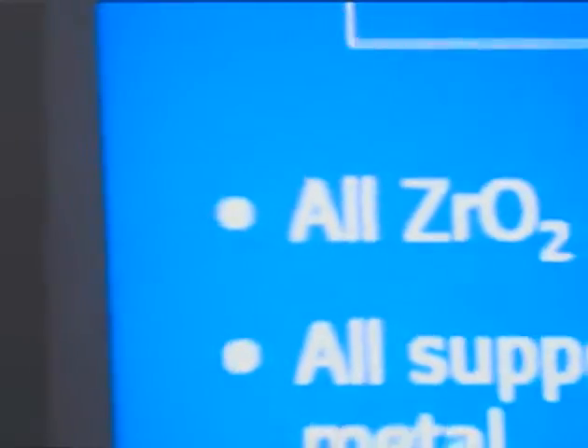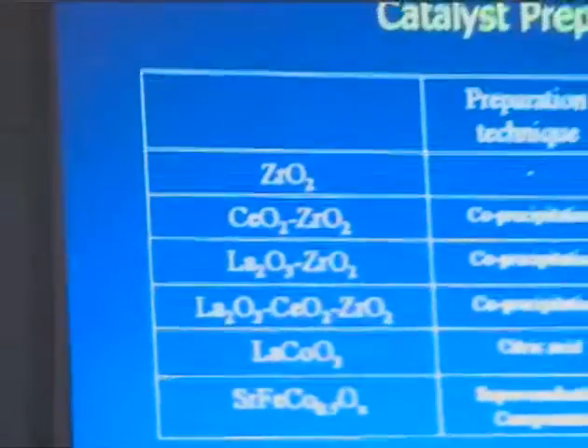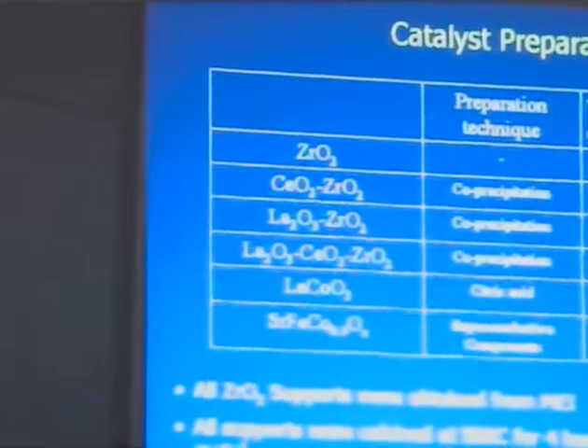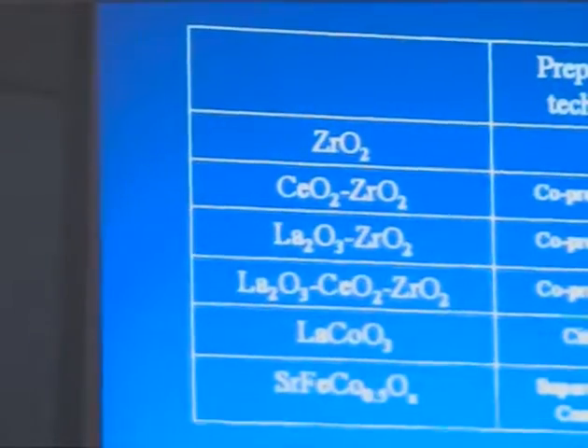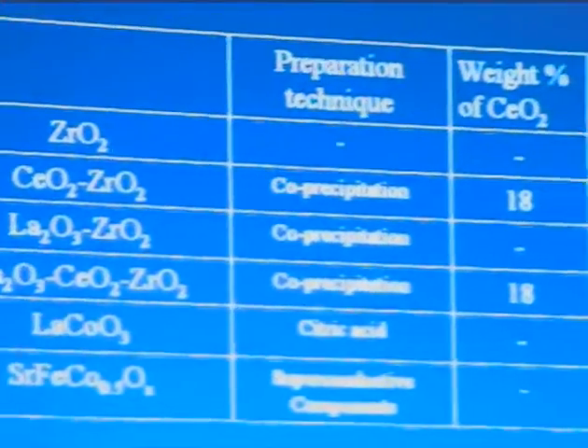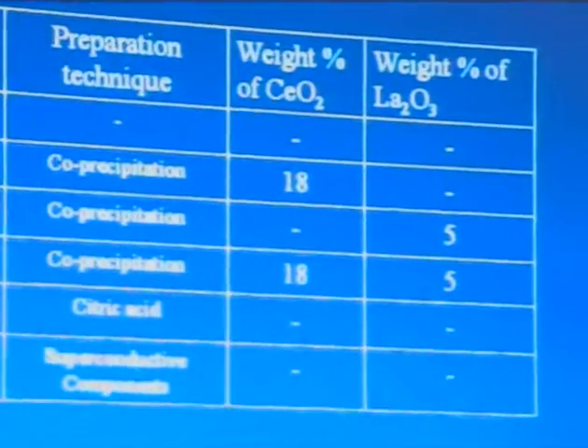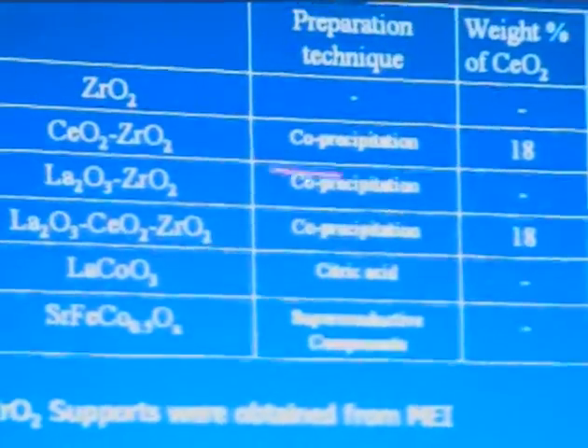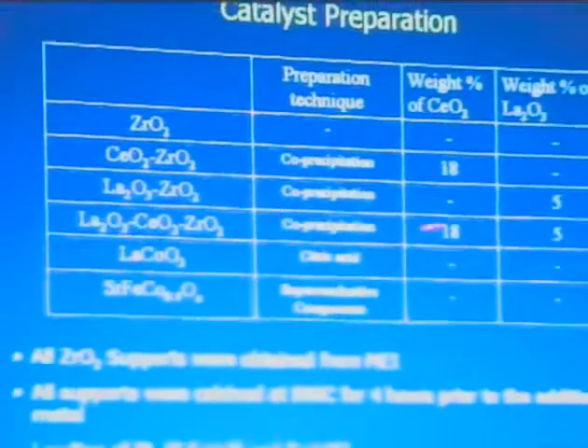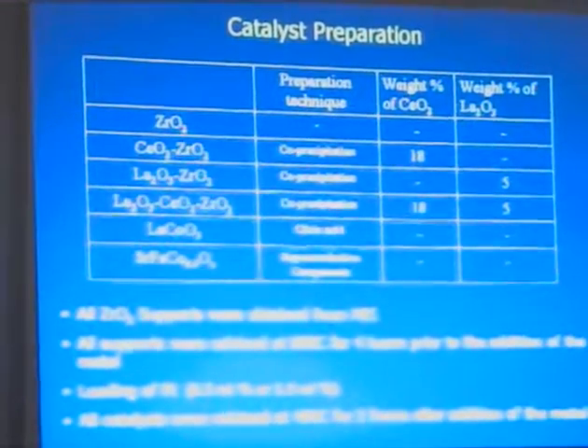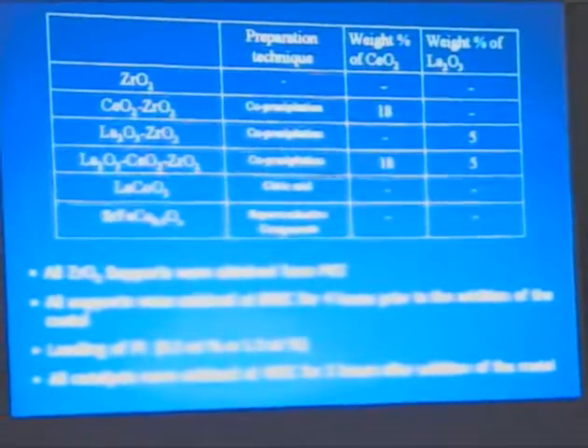The catalyst preparation: all of the zirconia catalysts that we have were obtained from MEI Chemicals. We prepared the lanthanum cobalt oxide using the citric acid method, and strontium iron cobalt oxide we obtained from Superconductive Components. We also have prepared a strontium iron cobalt oxide material ourselves in the lab, and we didn't see any difference between the activity in a citric acid preparation that we did and the one that came from Superconductive Components. On the ceria zirconia catalyst, we used the 18 weight % ceria zirconia. The lanthanum zirconia had 5 weight % lanthanum, and two catalysts had the same weight % of both of them to try and look at the effect it had by dual component catalysts.